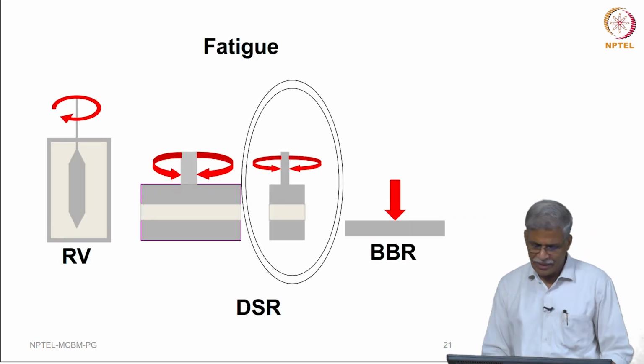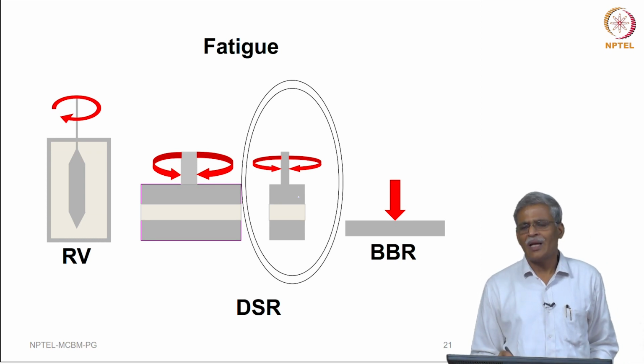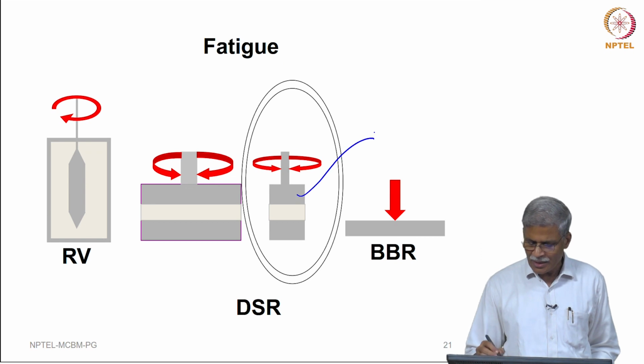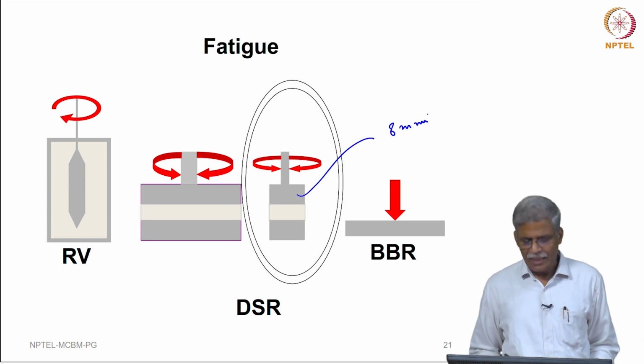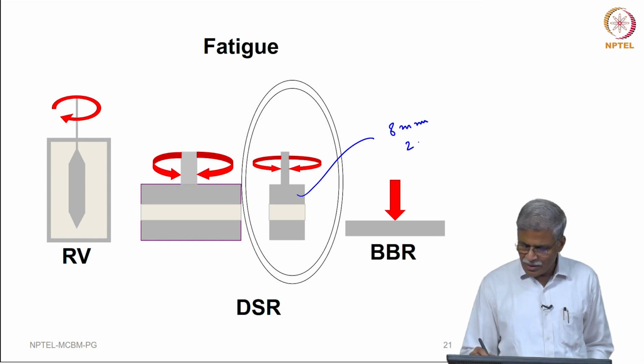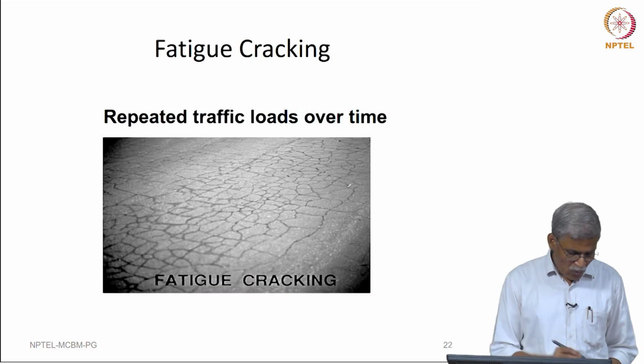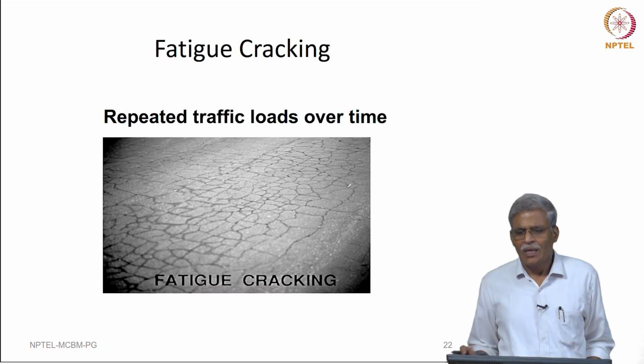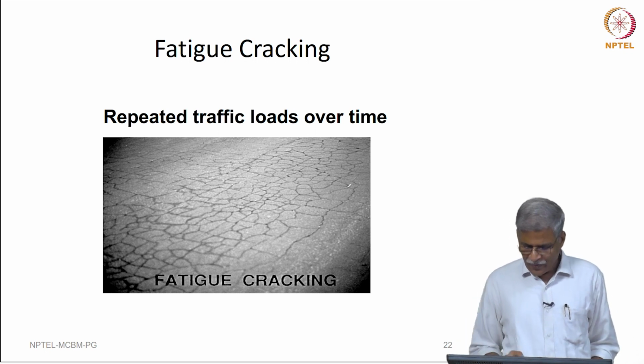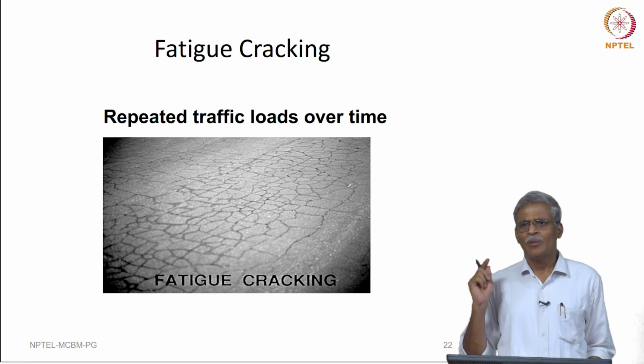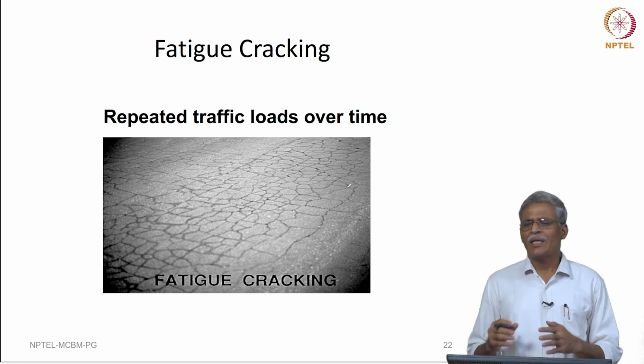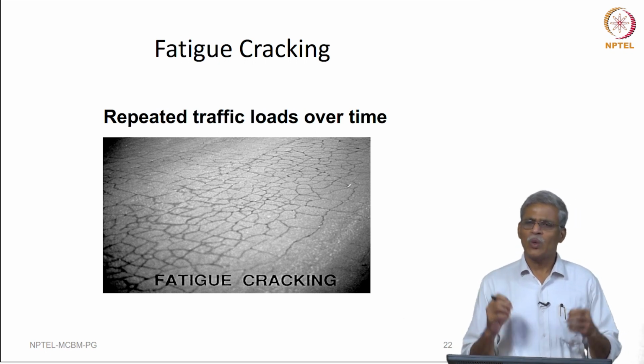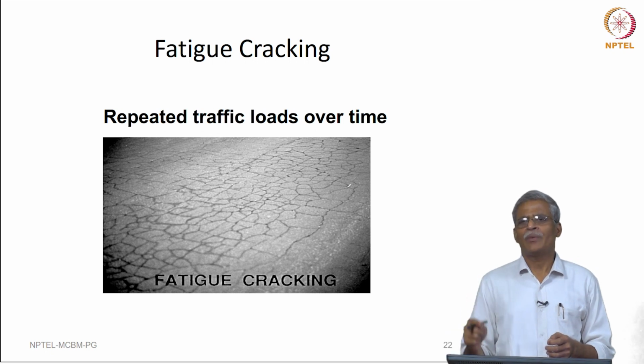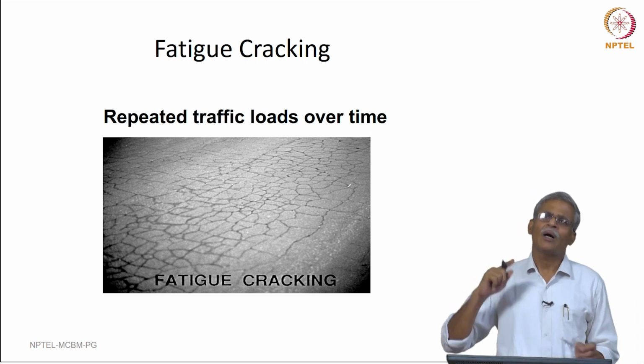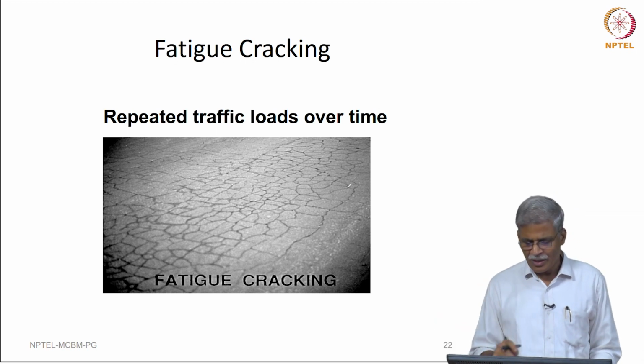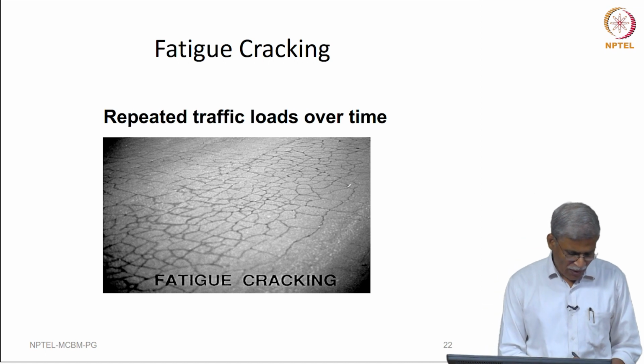Now let us talk about the fatigue here. When you look at the fatigue, it is the same DSR, dynamic shear rheometer, except that you realize the plate diameter is slightly less, and you also notice that the sample thickness is slightly more. Okay. So when we now go to this, you are going to have repeated traffic loads over time, and this is what is shown here as the fatigue cracking. Please understand, to emphasize again, that what we are trying to measure in the laboratory is one parameter on a binder, and this parameter on the binder is expected to tell us how the mixture will perform in the field for this specific condition. Okay, right.